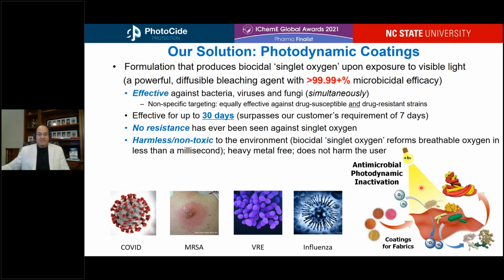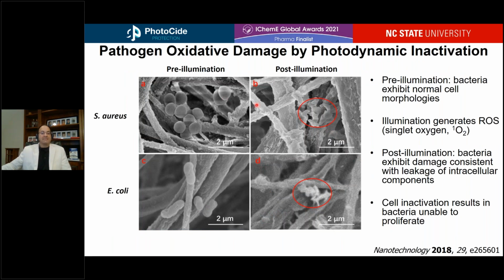And so whether it's against any of the pathogens that you see here on the bottom left of the screen, the way that our material works is that we can have a coating, as an example, that we apply to a fabric. We shine light onto that coated fabric. The molecular oxygen is activated to the biocidal form, leading to the inactivation of those pathogens. The inactivation of those pathogens can actually be seen here on these SEM images on some coated nanofibers that contain our photodynamic